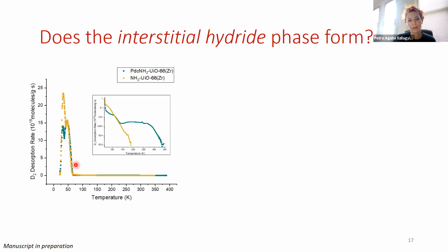So in yellow you see the empty framework, and in blue is the palladium-laden framework. The first thing you can notice is that there is much more hydrogen coming off the empty framework, and that is good because that corresponds to the lowest binding energy or adsorption enthalpy, if you wish. And of course, that should be the filling of the MOF pores. And we know that a lot of palladium is in there, so there is not so much room for the hydrogen.